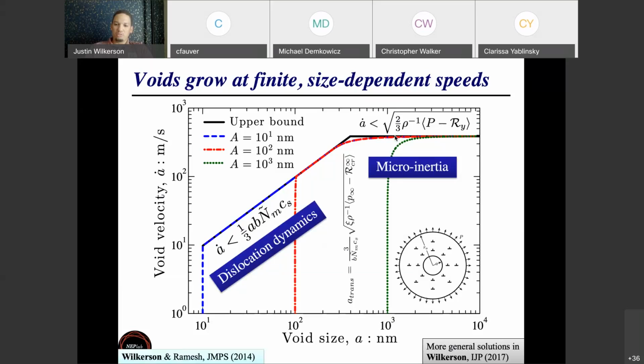And then I have some more general solutions in some subsequent papers. And what's really important, like I mentioned already, is that these voids grow at very finite rates. So you can see here, this void, its maximum void velocity is about 400 meters per second for this particular material with this particular density and for this particular loading state. And so it can't grow any faster than that.